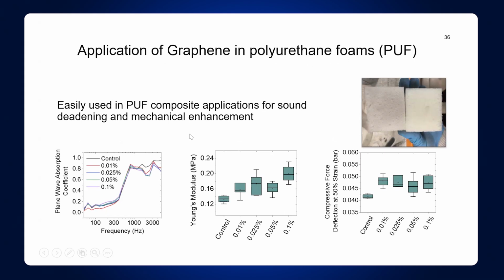And so, for example, you can see here how here's a foam cushion for the seats, and you see it's a little bit darkened. That's because of the graphene content versus the one that doesn't have any graphene in it. And it did everything that it's supposed to do, meaning that it absorbs more sound by having the graphene in there. It increases the Young's modulus, which is the stiffness of the material, and the toughness of it as well, and the compression force it increased. So it did everything that it was supposed to do.